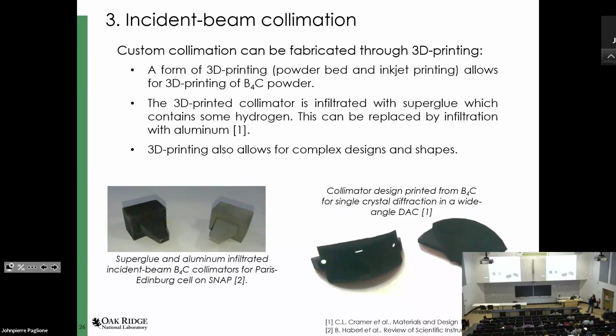So here are some of our typical collimators that we are using now. These little snout things here is what we use with the Paris-Edinburgh cell. So this front bit here is what points at the sample to make sure we only illuminate the sample and nothing of the pressure cell. And then these ones here are more complex shapes we actually printed for our diamond anvil cells for single crystal applications. Because there you want to rotate the cell in the beam, so you need a large sort of aperture where you can rotate around. So this is what we call colloquially incident beam collimation. It's technically not collimation, it's very sophisticated shielding, but it's been really crucial for high pressure experiments to make sure we only illuminate the sample and as little of everything else as possible.